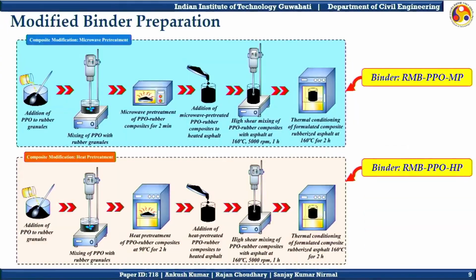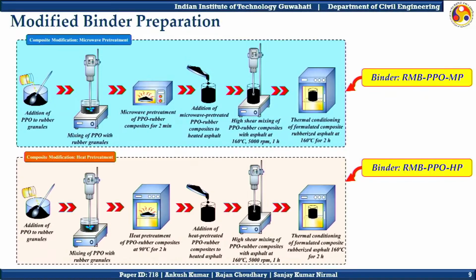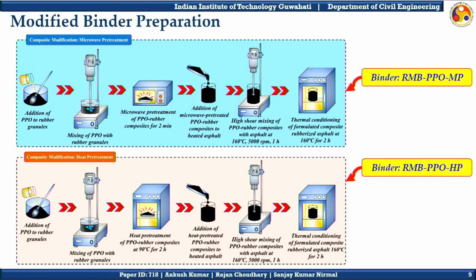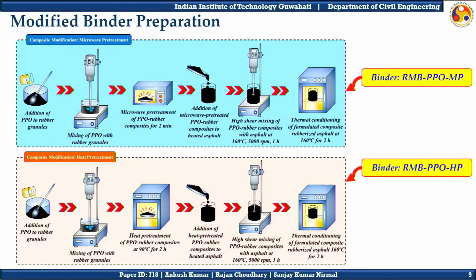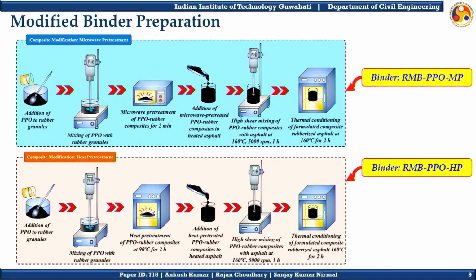In pretreatment approaches, for both microwave and heat pretreatment, PPO was first added to the EPDM rubber, and that mixture was stirred using a stirrer. Thereafter, that EPDM and PPO composite was microwave pretreated for 2 minutes in a microwave oven in the case of microwave pretreatment, and the EPDM and PPO composite was heat pretreated for 2 hours at 90 degrees Celsius in an oven. Thereafter, the binder preparation approach was the same, where the composite was added to the base asphalt and high shear mixed. Thereafter, the mixture was thermally conditioned.